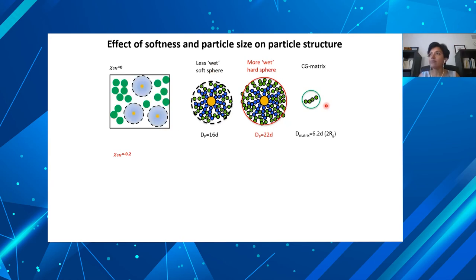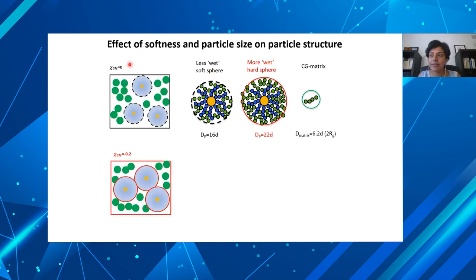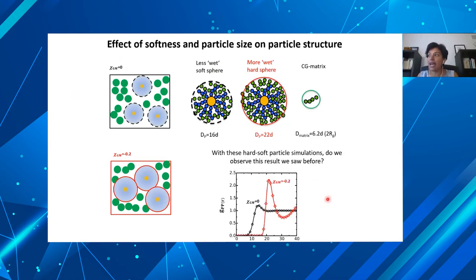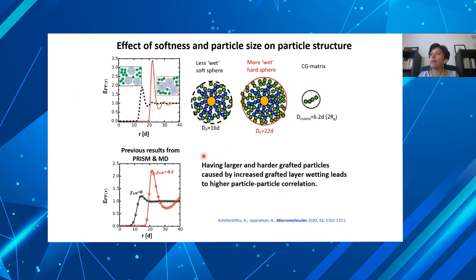What do we see? So essentially at that entropic limit, they should be dispersed because they should be soft and less wet and small. And at the higher attraction, they should be large, hard, and they should demonstrate higher pair correlation. So do we see that? Indeed, we see that. With the very coarse-grained simulation, you can see these images here. These were the radial distribution functions, particle-particle correlations. We see that it mimics what we saw earlier, proving our hypothesis.